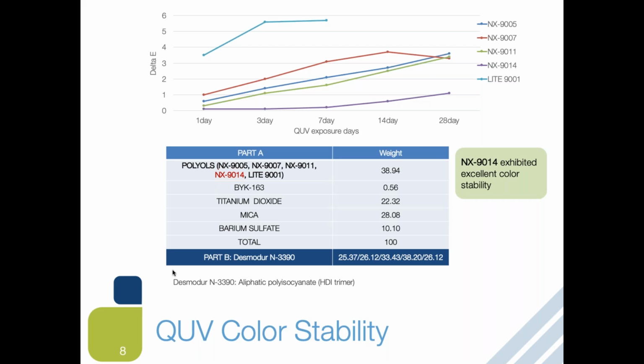So in this study, you can see the color stability by exposing your panels to a QUV chamber. We formulated the polyols curing with the HDI trimer, which is typically used for light, good color stability coatings. In this study, NX9014 has shown excellent color stability after 28 days of exposure, still maintaining the delta E around 1 and below, followed by 9005, 11, and then 7. 9001 has shown reduced color stability after 1 day, with delta E jumping to greater than 3.